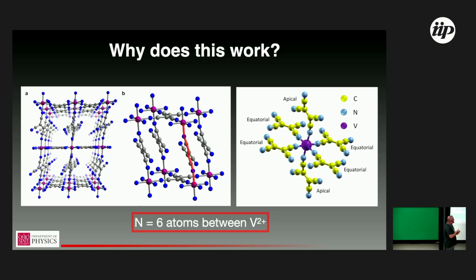So you have that octahedral coordination locally. We're not doing true, real single crystal growth, so the material's highly disordered. The way I think of it is it's polycrystalline with a grain size that's quite small. We're still trying to figure out how to get good measurements of exactly how small. 1 to 10 nanometers would be my guess, but just to sort of set expectations.